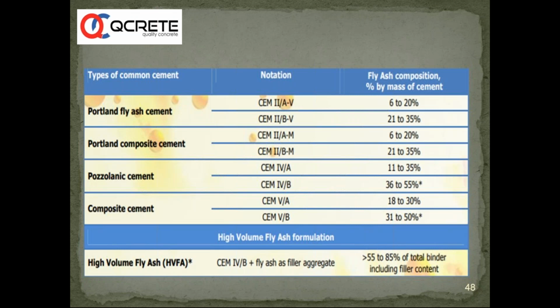in other countries. Especially, I'm surprised that in cold countries where the reaction between cement and fly ash is much slower when compared to a country like India or any tropical country, this amount of fly ash is being allowed to be used actually. And high volume fly ash concrete, they are permitting whatever is between 55 to 85% for various applications.